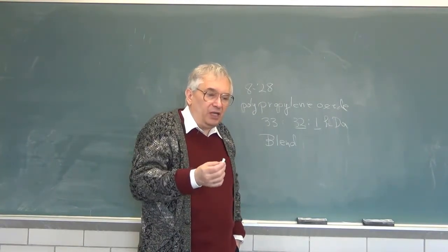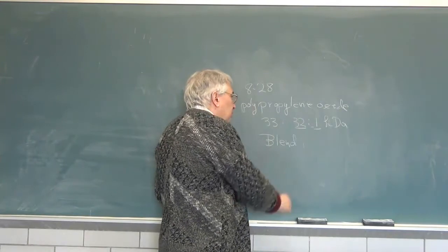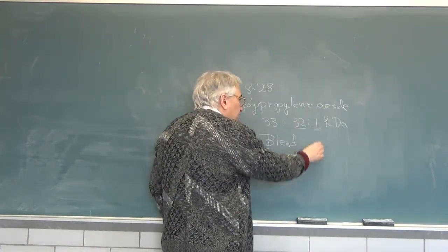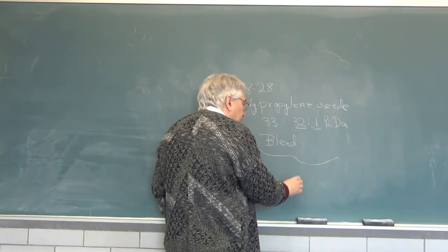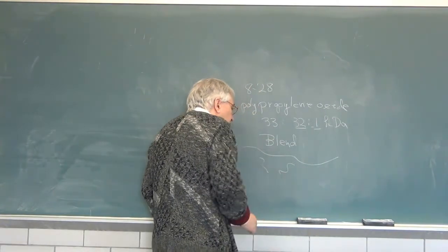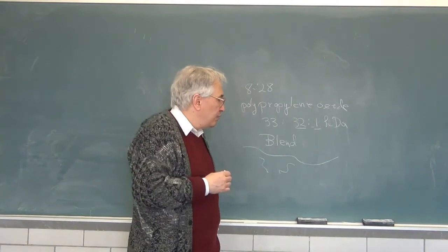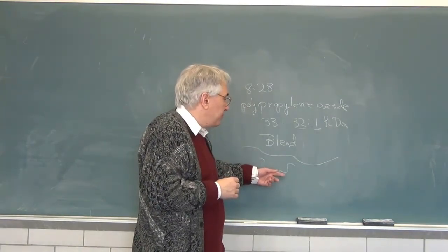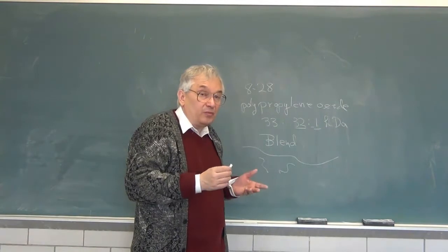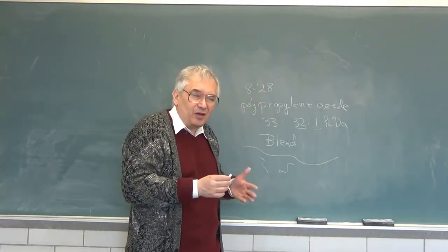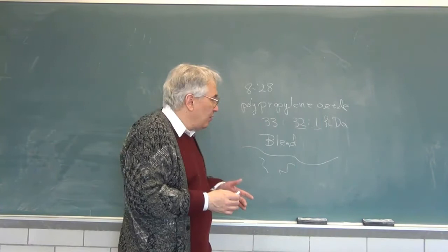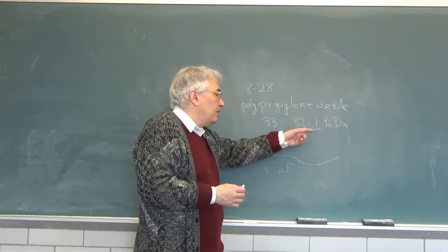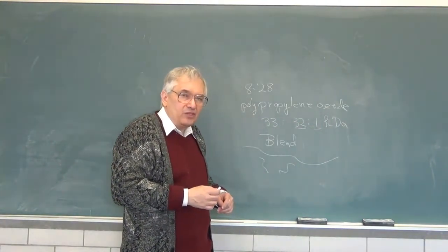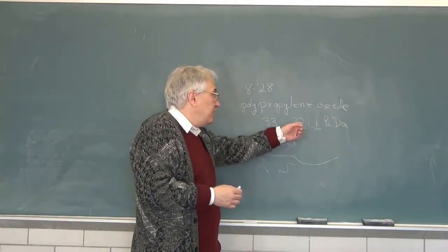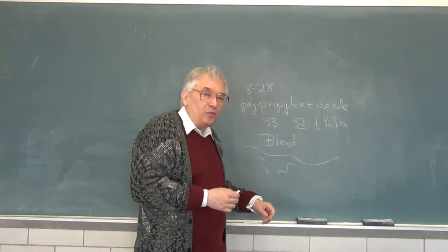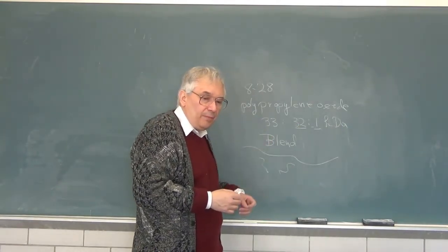Now, the virtue of a blend, yes, the molecular weights are very different, but the two chains are chemically the same. So you have long chains and short chains, and there is essentially nothing that persuades the matrix polymer that it should not be soluble in what is the solvent, which is more of itself, except shorter pieces. And therefore, you do not run into a solubility limit the way you do with some polymers. Instead, the combination is soluble in all proportions, and now you drop a probe in.